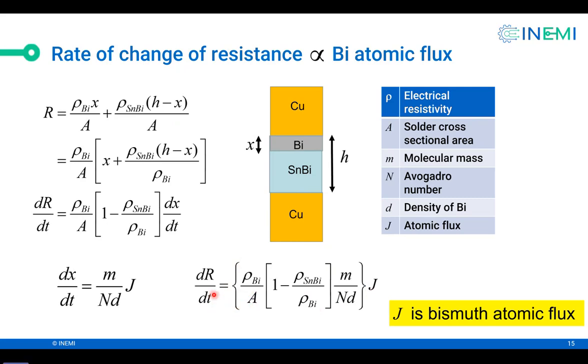So the resistance is increasing because of bismuth segregation, and the rate of change of resistance is proportional to J, which is the bismuth atomic flux, which is the rate of electromigration. So this is the rate at which bismuth is segregating at the anode. So this is justification for using the rate of change of resistance as a measure of electromigration.